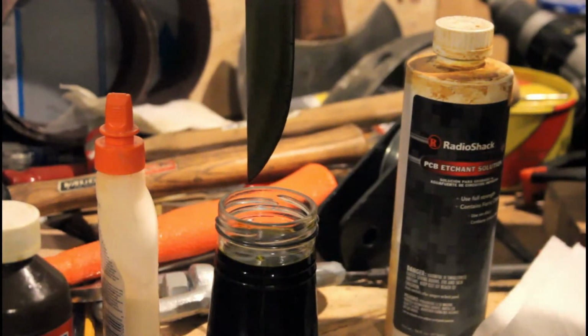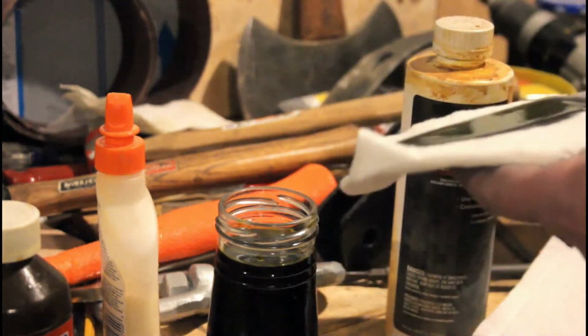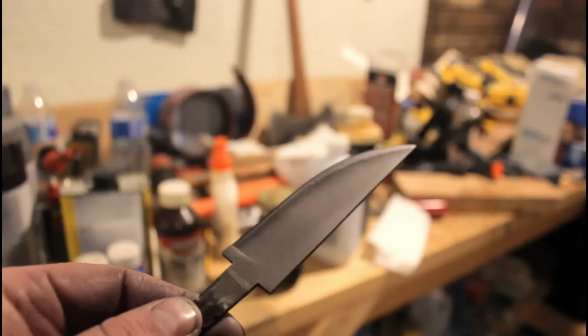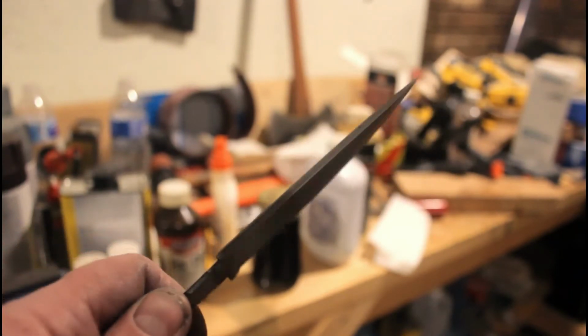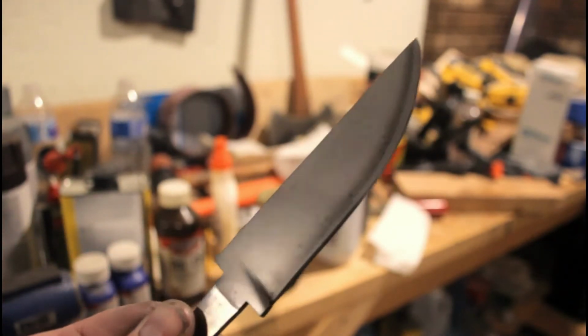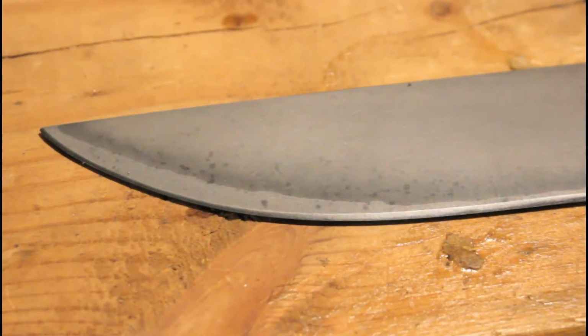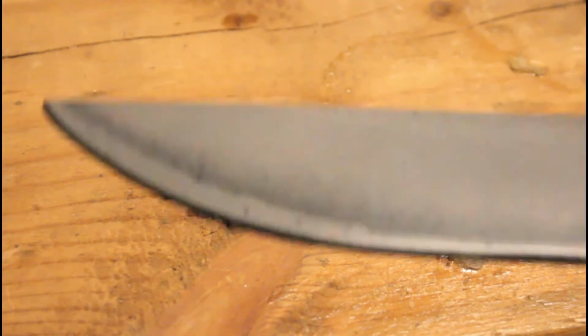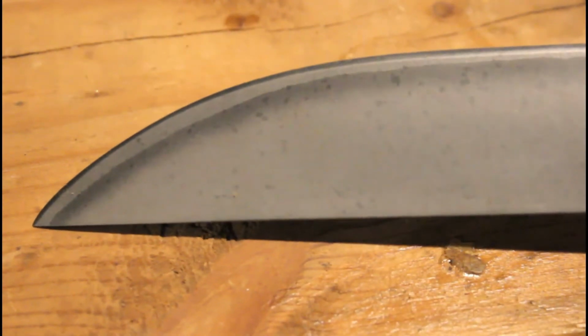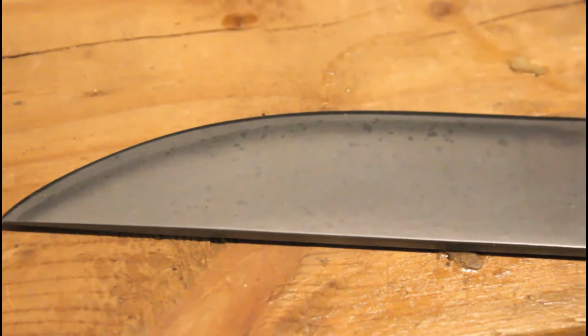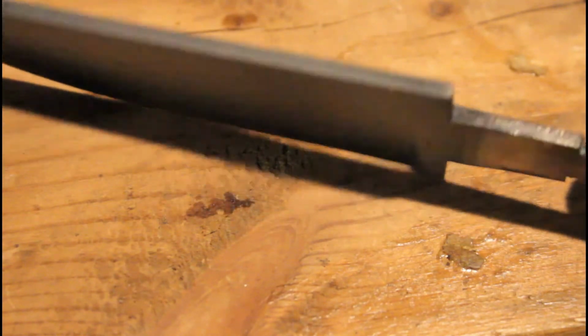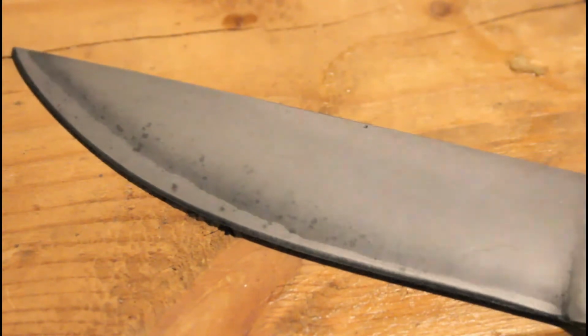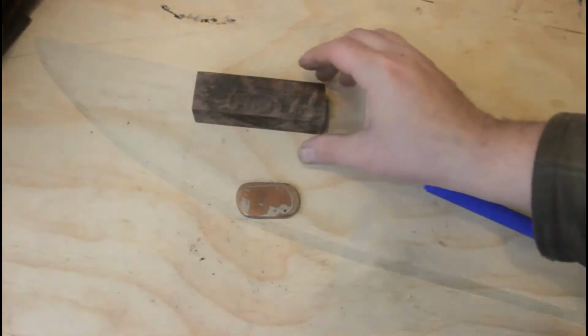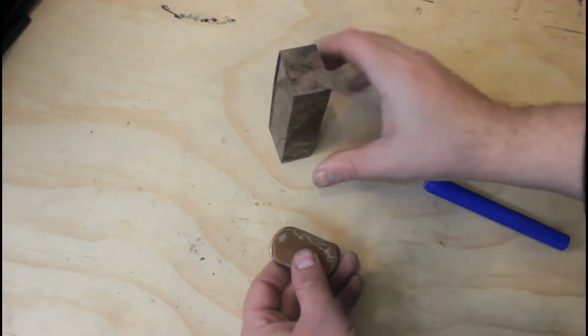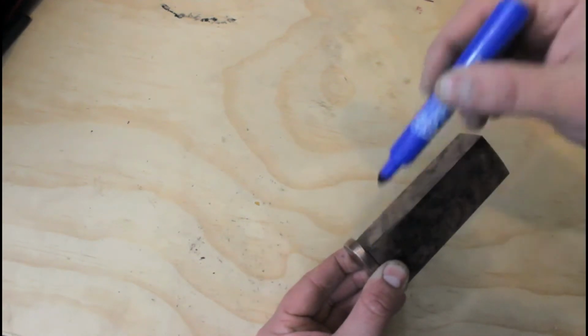After cleanup, the blade goes back into the ferric chloride for about 1 minute. We've got a bit of an unusual result here. I expected the high carbon edge to etch in much darker than the stainless steel. But for now, it looks like all we've done is etch the carbon transition line between the 52-100 and the 410 stainless. That's kind of weird. Anyway, it's time to set the blade aside for a while and move on to making the handle.